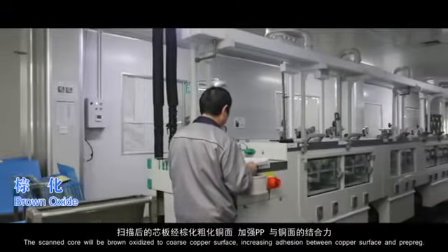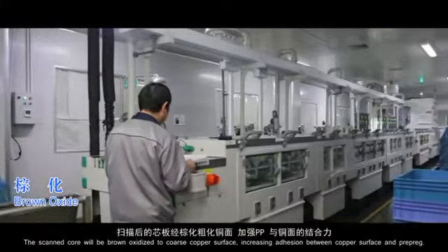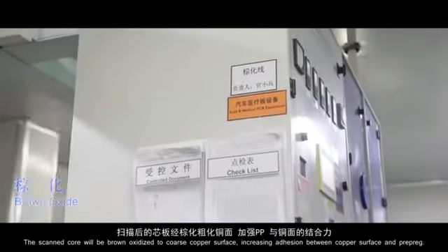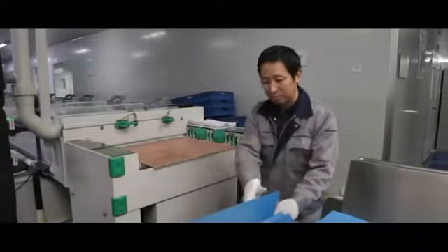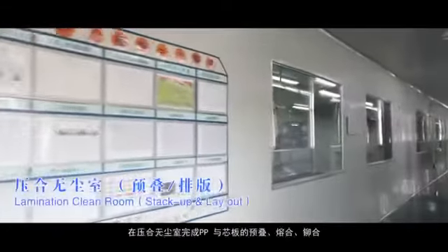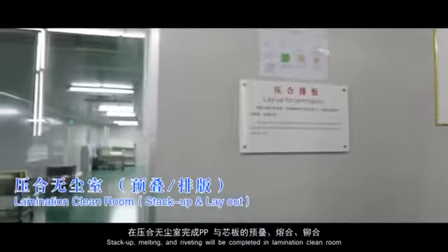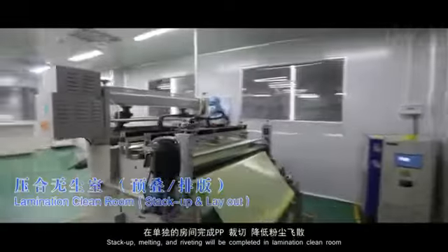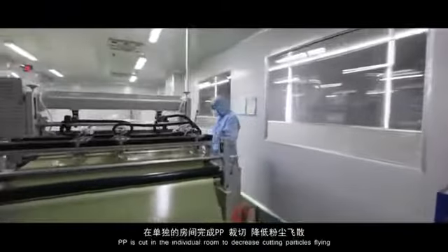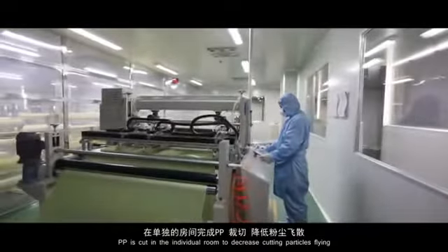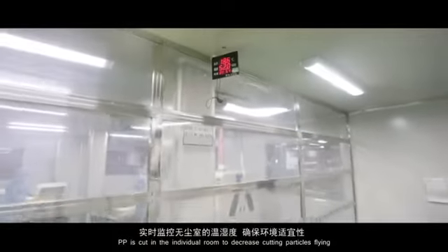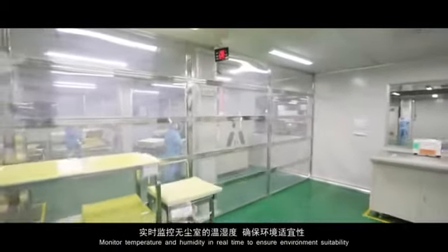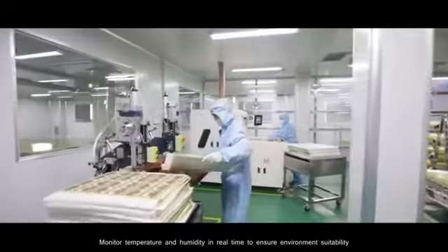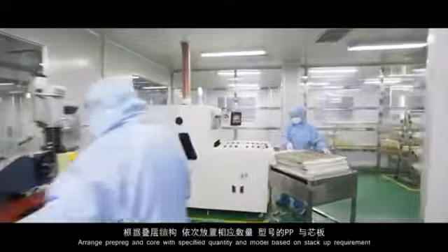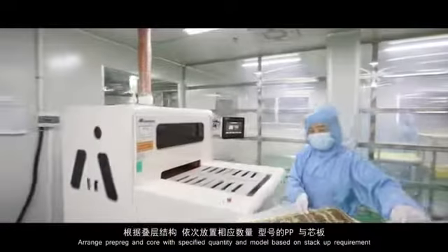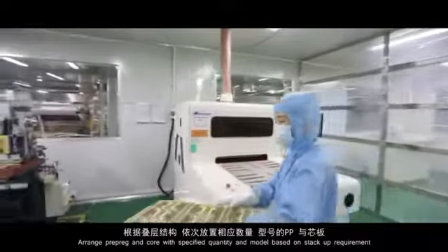The scanned core will be brown oxidized to roughen the copper surface, increasing adhesion between copper surface and prepreg. Stack up, melting, and riveting will be completed in the lamination clean room. Prepreg is cut in an individual room to decrease cutting particles flying. Temperature and humidity are monitored in real time to ensure environmental suitability. Prepreg and core are arranged with the specified quantity and model based on stack-up requirements.